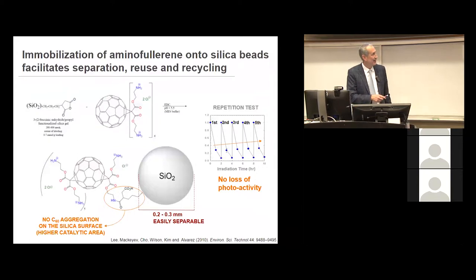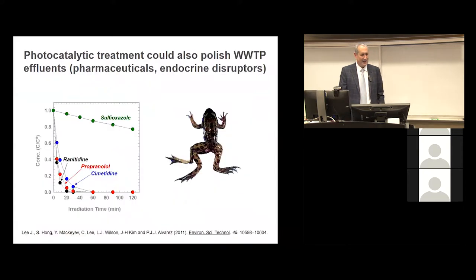So we were able to immobilize them using covalent bonds. In this case, we immobilized them onto silica grains to mimic a model for sand. We were able to reuse them over and over efficiently without loss of effectivity. And a nice surprise was that not only was this an effective disinfectant, but it was also destroying relatively recalcitrant pharmaceuticals and endocrine disruptors that right now are breaking through our wastewater treatment systems.